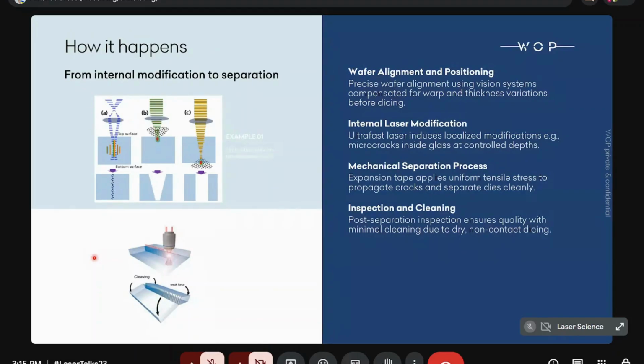If you make this scribing or dicing, whatever you call it, you make a modification in the glass material, and then by adding mechanical force, be it bending on a sharp edge or stretching tape, you simply mechanically separate your material along these dicing lines. So again, here you can see the main stages of laser dicing. One thing is to place it very precisely according to the drawing you have. You make internal laser modification and then separate it mechanically.